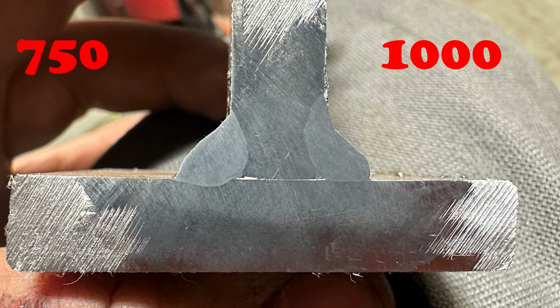Now the 1000 degree one, which that sucker was glowing red that you would think would have melted halfway through that, more or less just melted in the upright plate and barely stuck to the bottom. Now this could be because Owen favored the top plate due to how much that molten pool was sinking, so that might have something to do with it. But again, even at 1000 degrees, it's not punching in there and fusing the plates together far deeper than even room temperature. Neither one of these are a miracle in comparison to the room temperature.